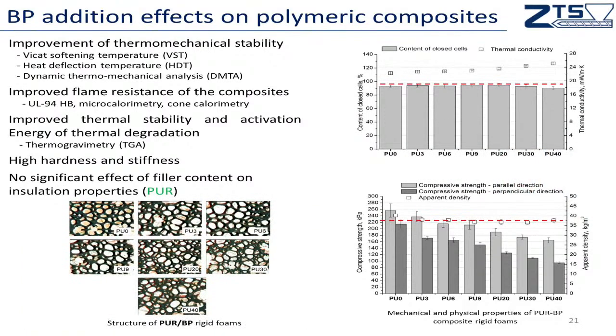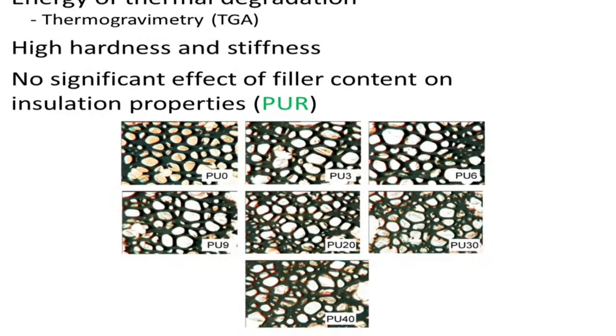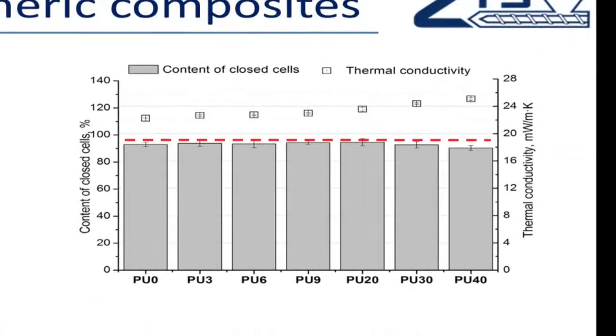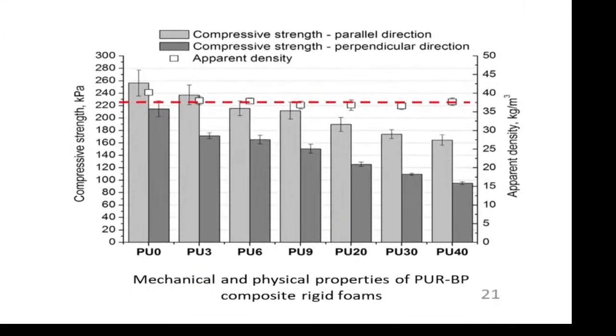Okay, so then if we move to the next slide, we can see also that addition of the basalt powder compensates for the lack of part of the polyol; the hydrogen bonds contained in the chemical structure of the material show us a comparable structure of the final products. So this is really important. The content of closed cells that are responsible for the thermal conductivity is almost not changed, and the structure of the material is also almost the same as in the case of the unfilled polyurethane. So this is also really good information for us and our industrial partners.